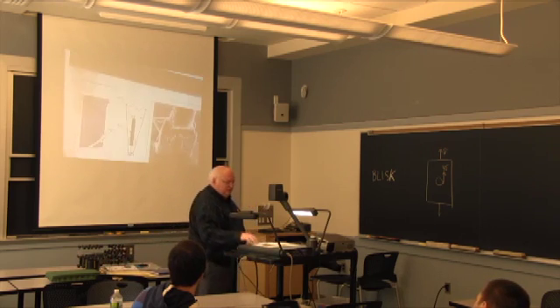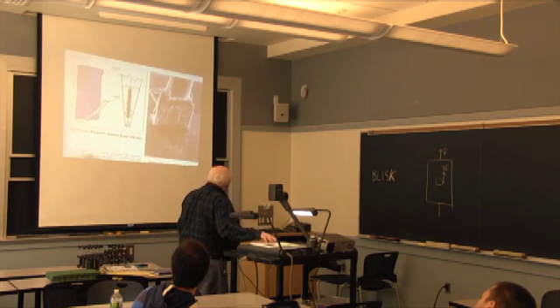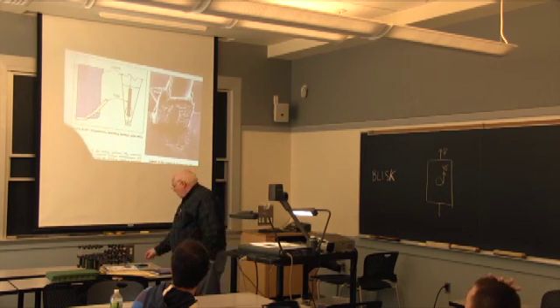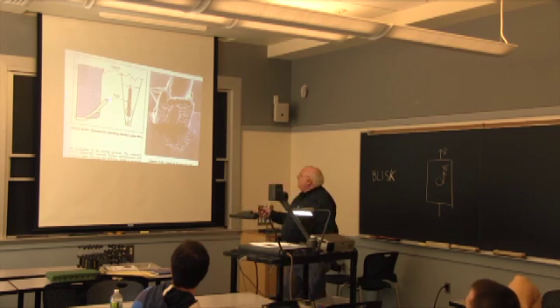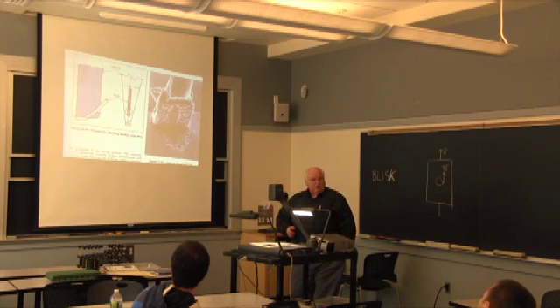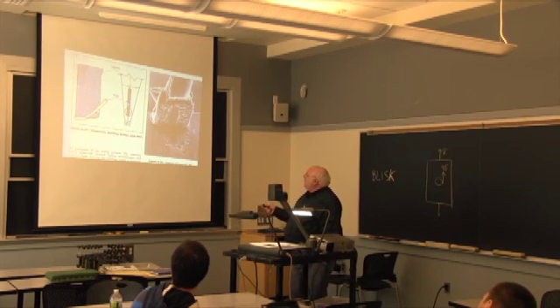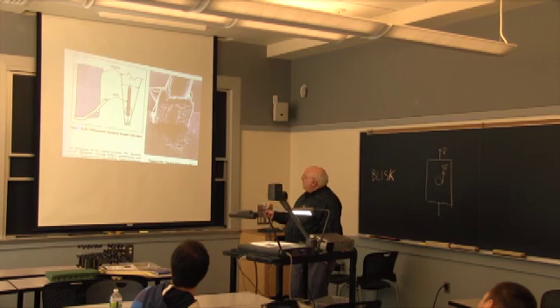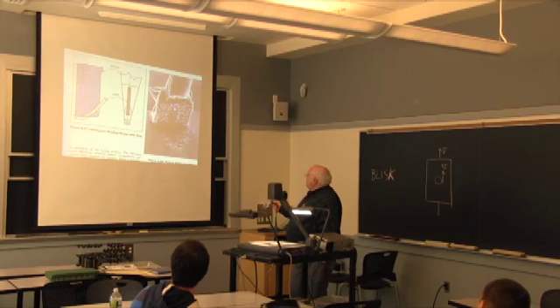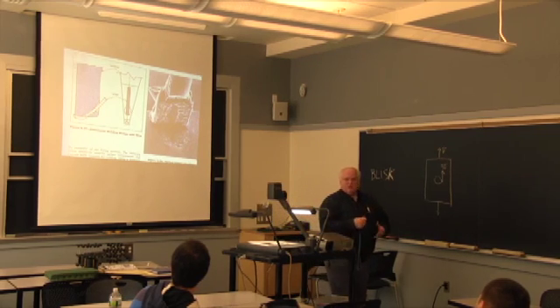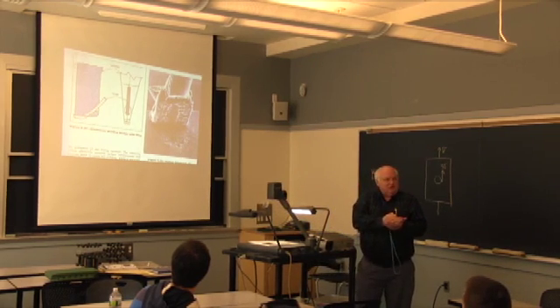Okay, and here's a picture of it from the Welding Handbook. This is actually one that they started to break apart, but the tooling looks sort of like a sewing machine, except you're using a thin gold wire rather than a thread, and you feed the stuff through. The head comes down, squeezes the gold into the surface, and actually spreads it out. So here's the 1 mil diameter wire. See this non-bonded region in the center? That's called the dead zone. That's where you have a straight normal force and no shear.